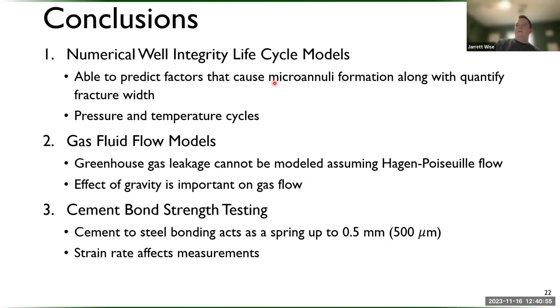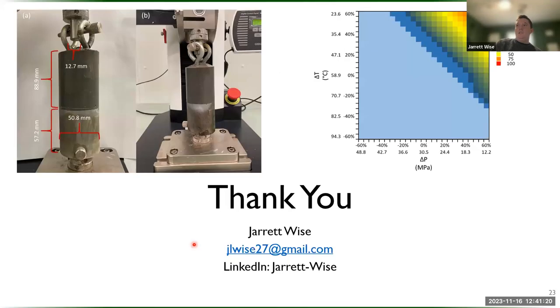And I didn't cover it here, but in some of the papers, we show that the effect of gravity is actually important on gas flow, which you wouldn't think, since the density is so low. And finally, we looked at some of the cement bond testing, which just shows that cement to steel bonding acts as a spring up to about 0.5 millimeters (500 micrometers). And then strain rate effects measurements. And that's all I have.